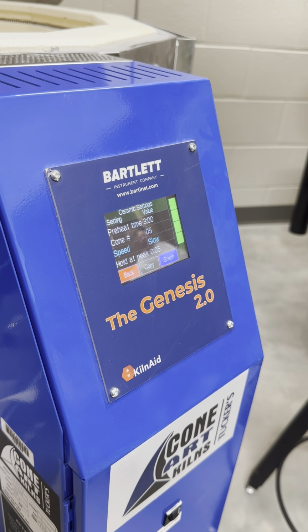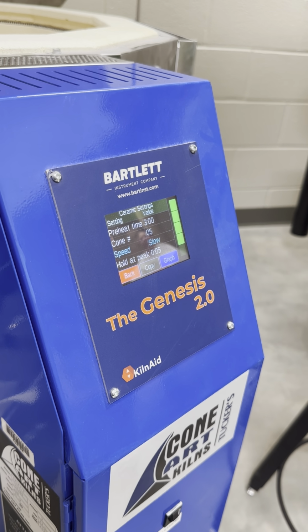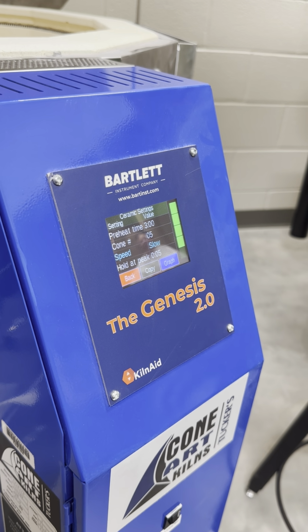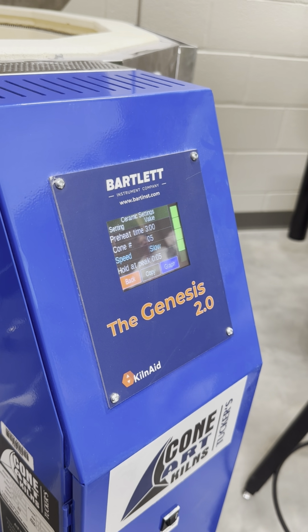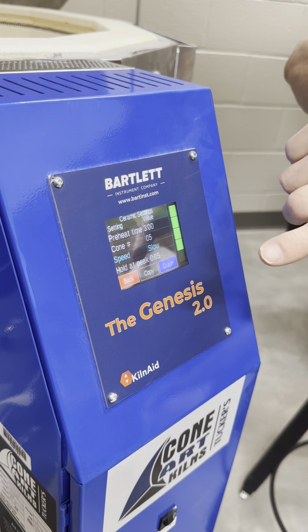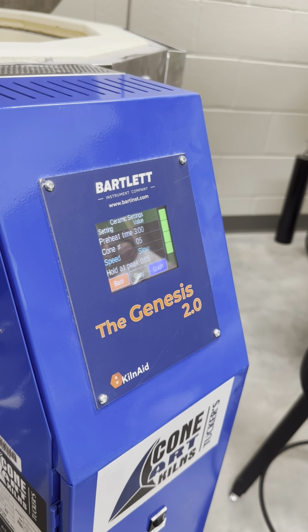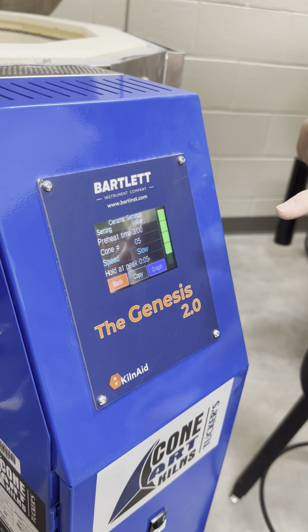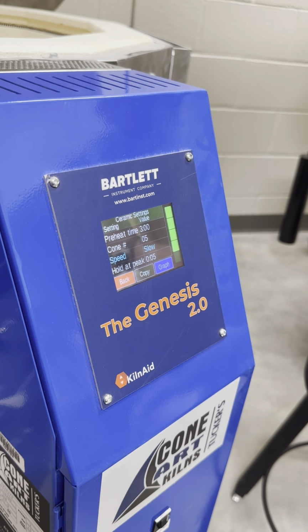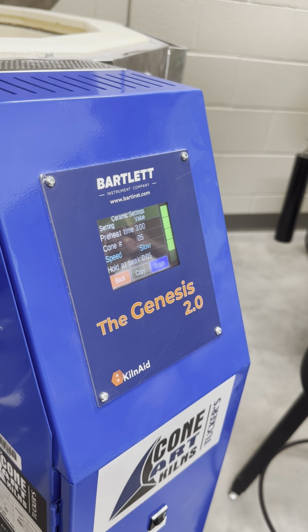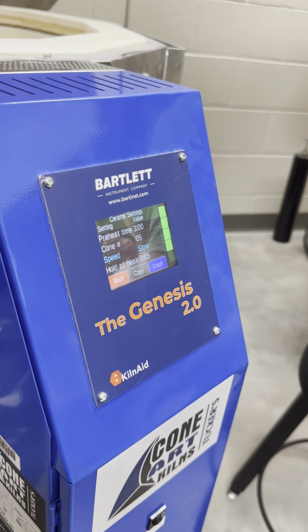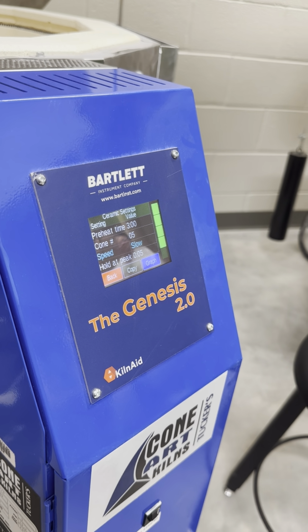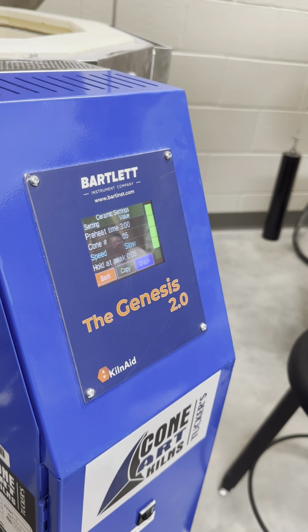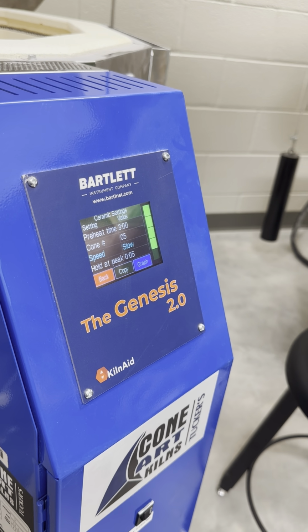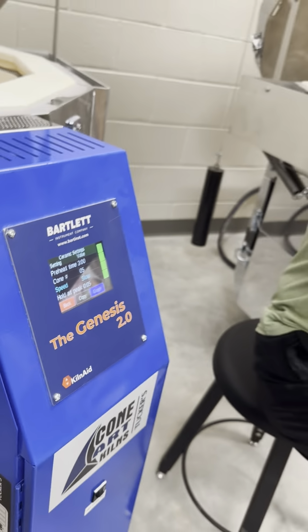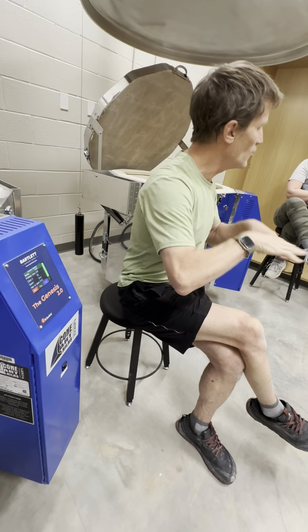The only reason you ever want to hold at the peak is if you're using glazes that are crystalline, that make crystals. There's actually a program in here for that though, so I wouldn't even mess with this if I was gonna do that. Or if the glazeware was getting pinholes. And this is a whole nother thing, so I would just take a deep breath and not worry about that right now. If you're getting a lot of pinholes, and we're firing a glaze kiln, it typically means it needed to hold a little bit longer so that those pinholes melted out.